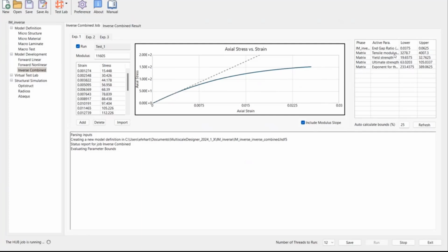If you work with that process, we always had this communication that this end gap ratio should be somewhere between 3 and 8%. I used this inverse process on a couple of data sets, and I could find a lot better fit to the measured data with a higher end gap ratio, something above 10%, between 10 and 15%.